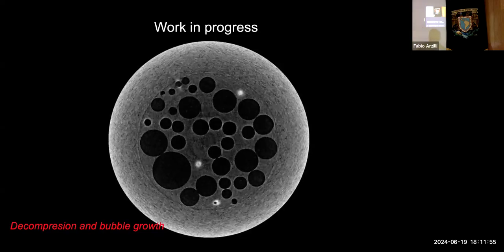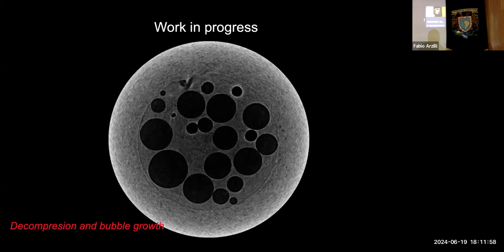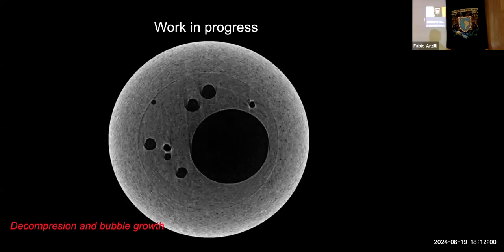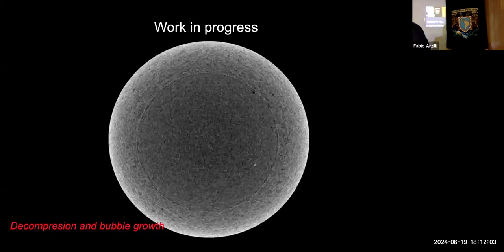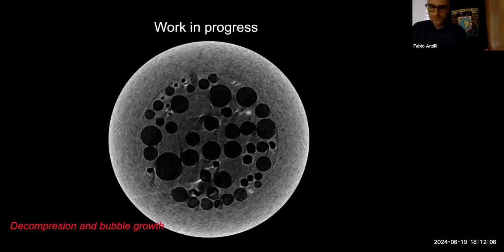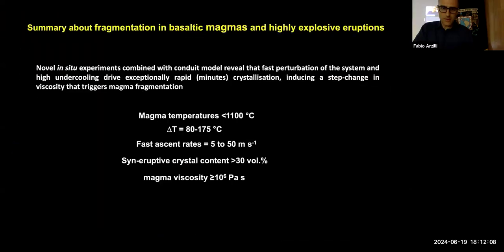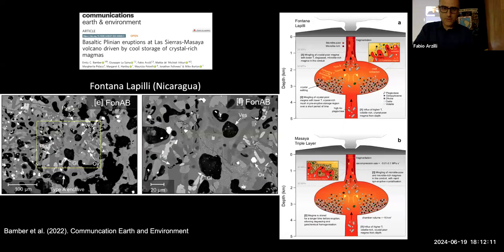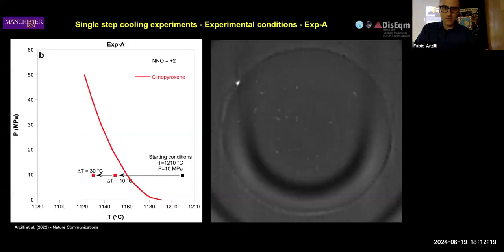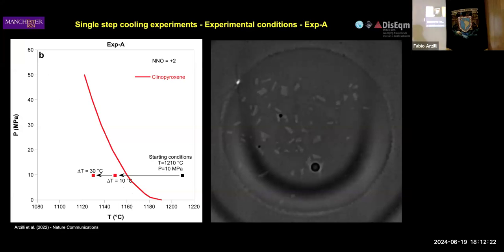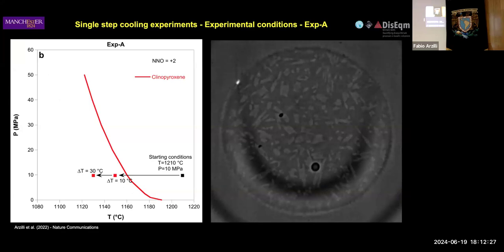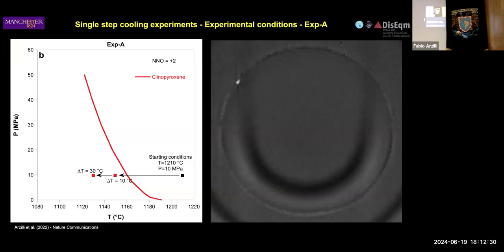And your question is surprising. By 1,000 degrees, the sample is already crystallized. Yes, basaltic. I don't know which one you refer to, but I can show you here. For instance, the clinopyroxene liquidus is here. So before 10 megapascal, already 1100. The plagioclase is more or less here, so it's a lower temperature.